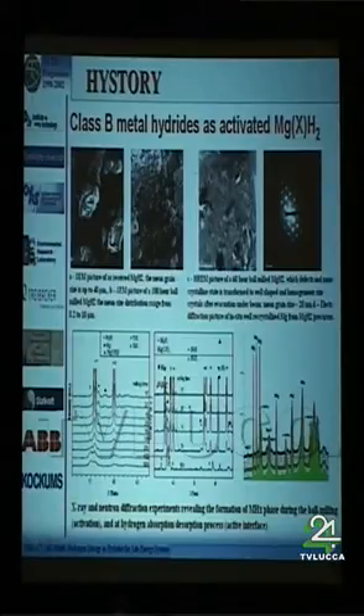Also, we have evidence that when we ball mill for a certain time at a certain energy, magnesium hydride with a catalyst, we got effectively very amorphous material, and many defects have been installed in the material. But after one cycling, it is very interesting to know that the magnesium powder crystallizes in very small, beautiful sized nanocrystals of magnesium. And this is a very interesting point, because it is known that hydrogen can diffuse very actively in between the small size, maybe 20 nanometer single crystals.